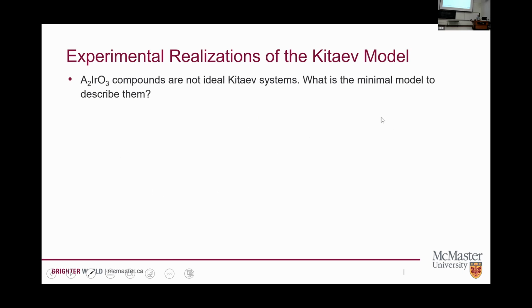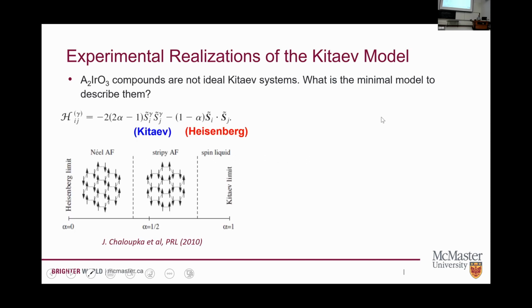And at this point, it becomes an interesting challenge to see what the minimal model that we need to describe these materials becomes. And it turns out that if we start to introduce other terms, the phase diagrams can get more complicated and more interesting pretty quickly. So if we have the simplest modification, we imagine we've got these Kitaev magnetic terms and some Heisenberg magnetic terms. Then if we tune the ratio of these two interactions, we can go from this quantum spin liquid through a stripy antiferromagnetic state into a more conventional antiferromagnetically ordered state.